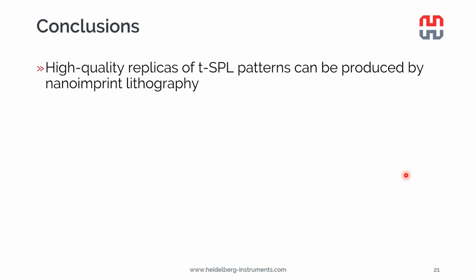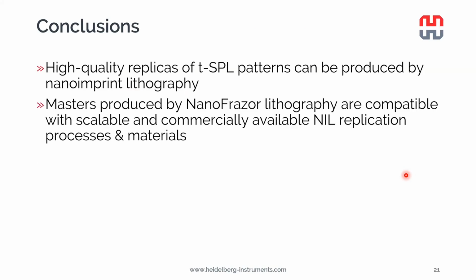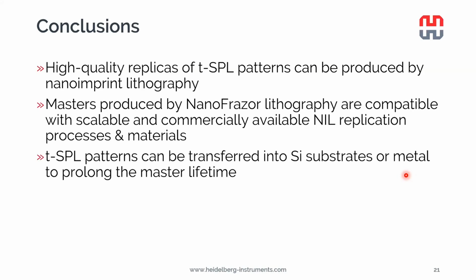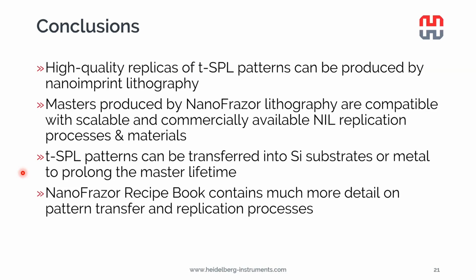Okay, so to conclude, I've shown that the NanoFrazor can be used for making very high resolution masters for nanoimprint lithography, and high quality replicas can be produced out of them. The masters are compatible with scalable and commercially available nanoimprint lithography replication. As I showed, we have worked together with 3 companies, and with all of these, we had no major complications regarding the processing and compatibility of materials or processes with what we are doing. Also, the TSPL patterns can be transferred into silicon substrates or even metal to prolong the master lifetime. The metal masters can also be used for very high volume manufacturing by the injection molding approach. And the NanoFrazor recipe book that was already mentioned contains much more detail on pattern transfer and replication processes as well. Thank you very much for listening.